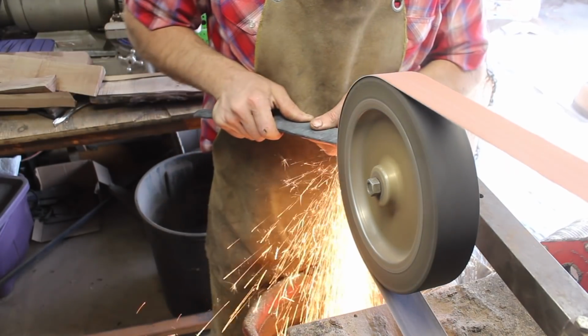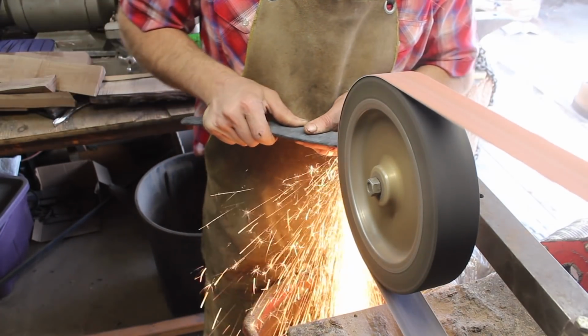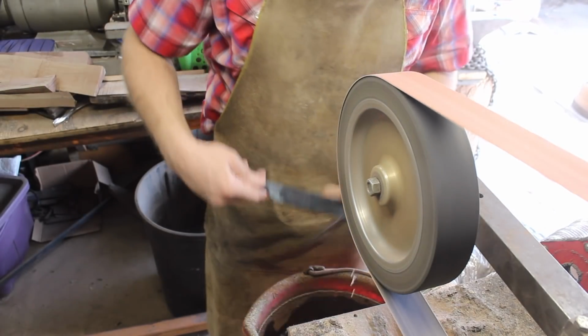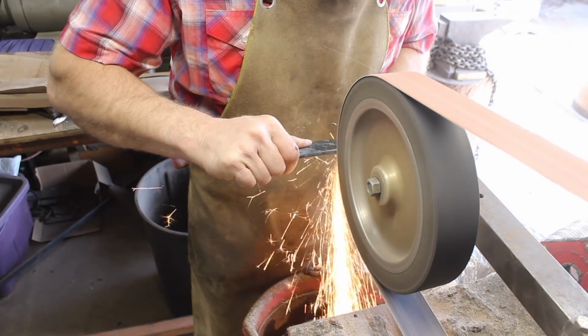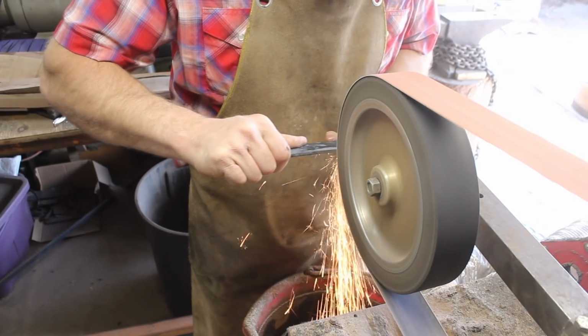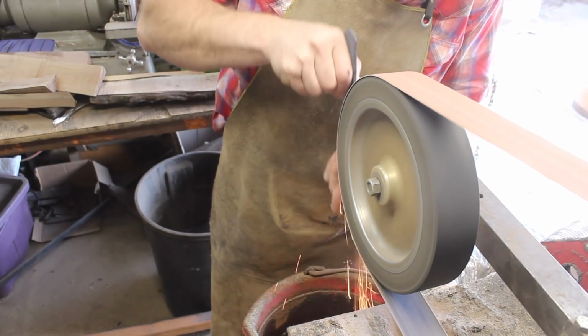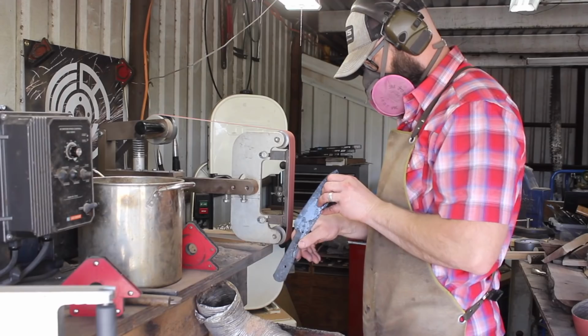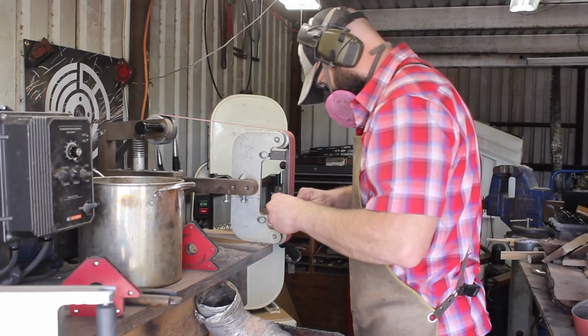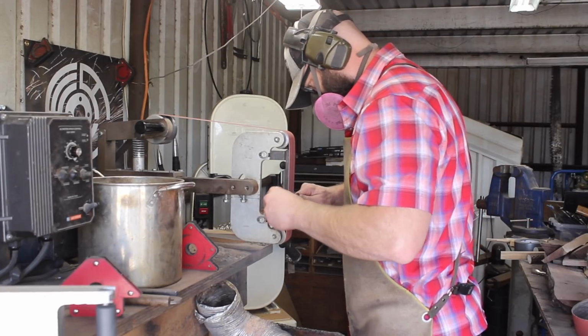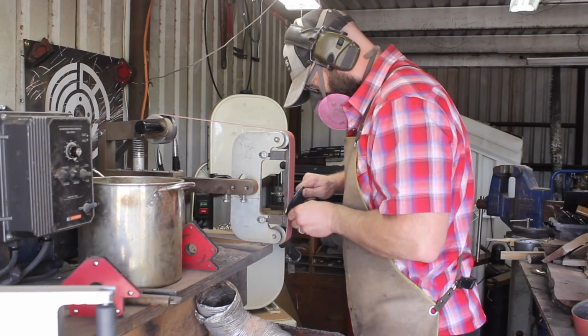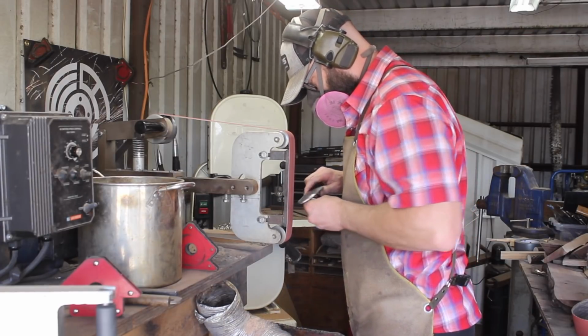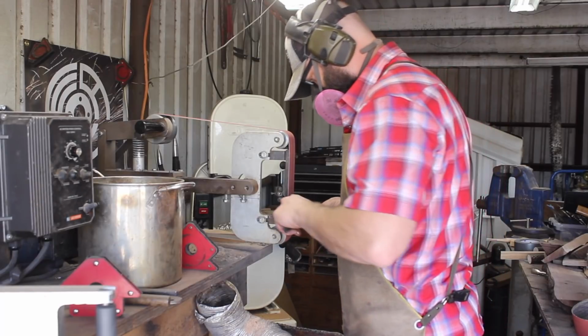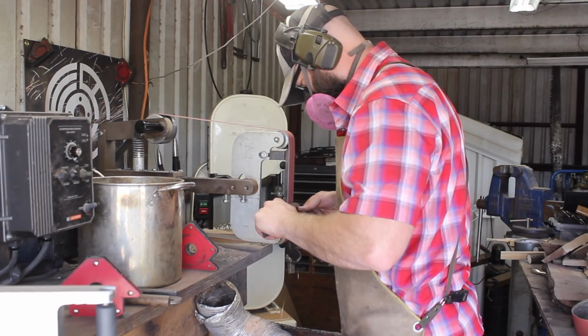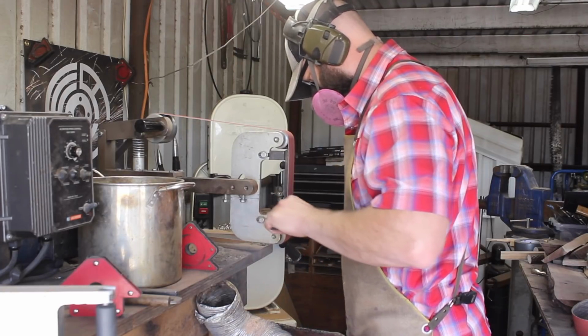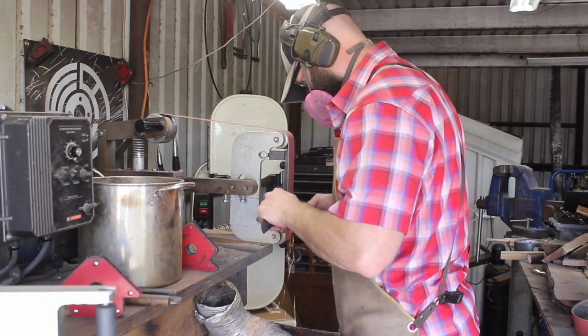Our blade has been normalized, and we've run a couple of grain refinement cycles on it as well. It's now in the best state that we can make it to transform it into the hardened phase of steel known as martensite, which will give us the best blade possible. Before we harden it, I want to grind out the blade shape a little closer to finished dimensions and also grind in most of the bevel. This is going to minimize the amount of grinding that we have to do on a hardened blade, and also make things more uniform, which is a good thing going into the quench. If you have different thicknesses of steel, even on a very small scale, that can lend to uneven cooling in the quench, which can often cause warping of your blade.